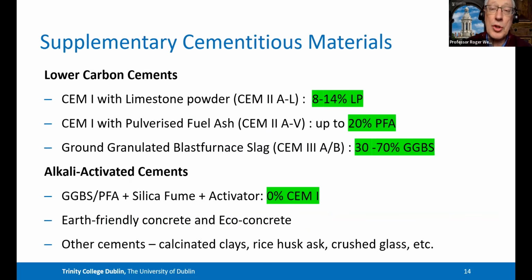So the types of cements, again, we should recognize the progress that has already happened and exists. So our CEM I, or our traditional Portland cements, have now been largely replaced by CEM II/A-L. And that uses less cement, or less clinker, as I should say. Its composition is different due to the use of limestone powder without any deleterious effect on the performance of the cement. And similarly, other manufacturers are using pulverized fuel ash in the same way. And then, of course, in Ireland, we can combine that with slag up to 70%. And again, if you're using 50, 60, 70% of GGBS, you're using that much less clinker. So these, including the CEM II/A-L, are all lower carbon cements, effectively. So we have gone some way, but we've an awfully long way to go.